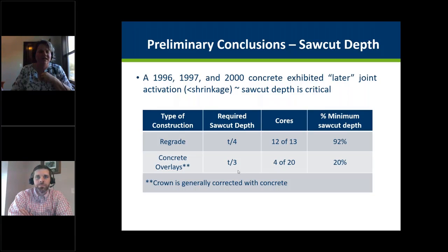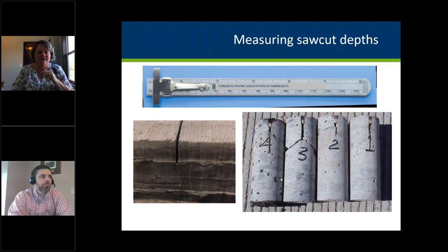A couple things that we saw when we went back and looked at these cores was the saw cut depth. We found that we were not always getting saw cuts as deep as they should have been, so we weren't seeing the joints activate. The joints don't crack all the way through. Any of those de-icers that get into those breached joint seals are going to sit there and just start to churn and cause damage. So we really focused on trying to make sure we were getting saw cut depths.